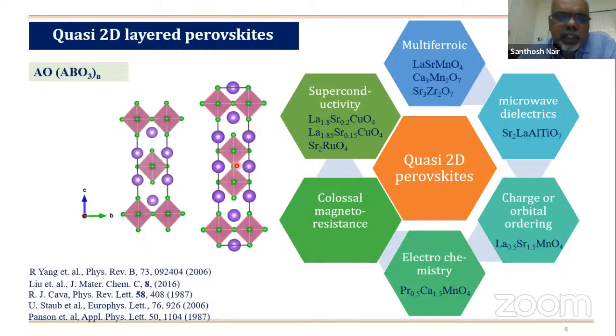So in essence, you increase the distance between the perovskite blocks, thereby reducing the interaction along the c-axis. So the magnetism or the electrical properties are more confined. It's not completely confined, but more predominant in the XY plane rather than along the c-axis. So in some sense, you have gone into a pseudo-2D system. So this has been studied.